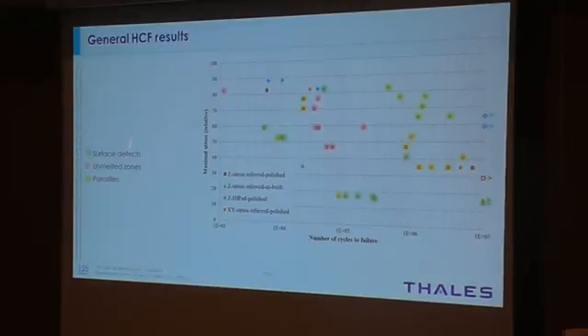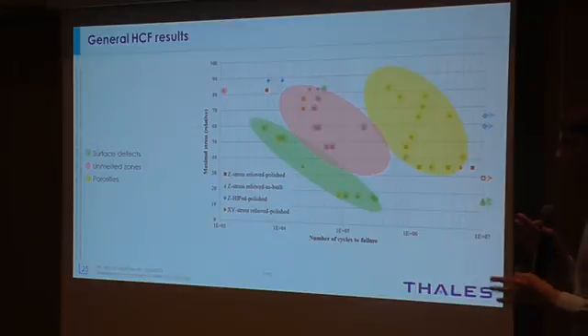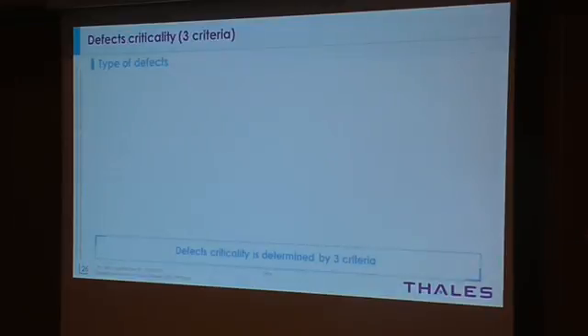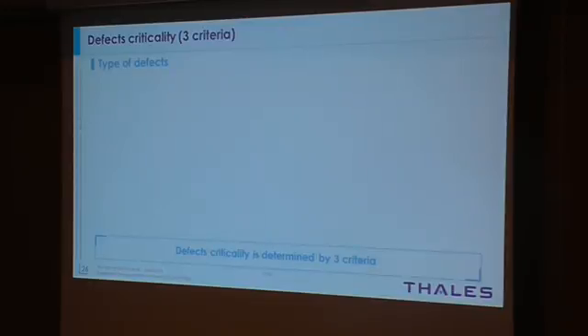When we plot all the specimens together, we can see three zones. So at higher number of cycles, the yellow zones, which are porosities, in the middle the unmelted zones, and on the left the surface defect. And with this we could determine three criteria to evaluate the criticality of defects. This is important for Thales to know what we have to control and how we will control them.